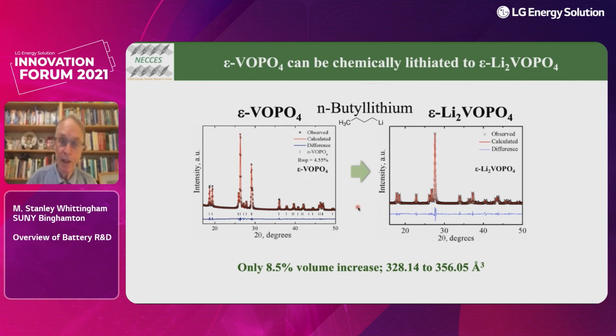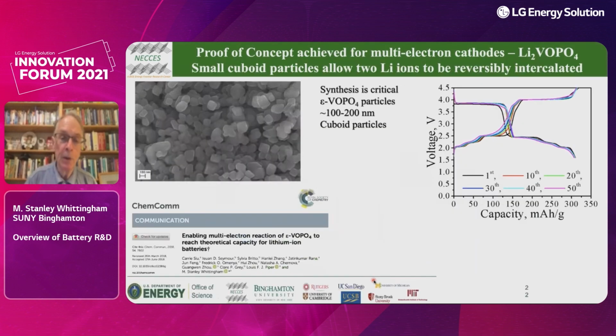And this chemical study was very promising because putting 2 lithiums in this lattice, we only saw an 8.5% volume increase. So this is less than the volume increase of, say, graphite. So using this technique, we made these cuboid particles, about 100 to 200 nanometers in size. We then mixed these with graphene. We found graphene was much more effective than carbon black. It has a much higher aspect ratio.